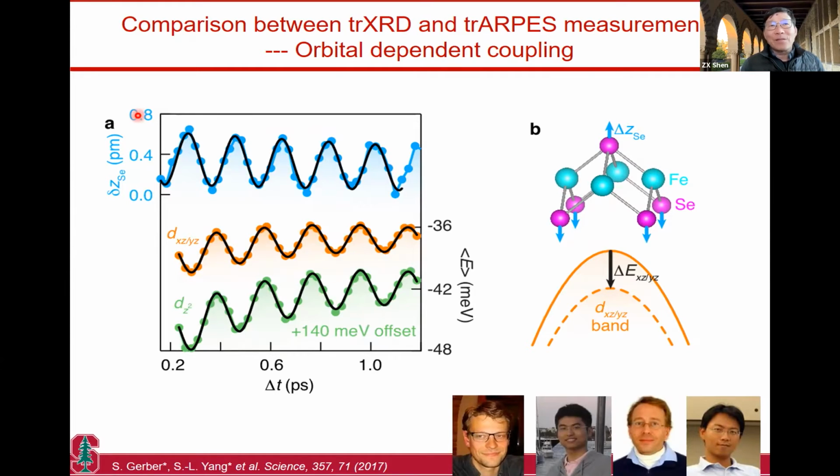So you better not change the lattice constant by 1% or more, because chances are if you change the lattice constant by more, you may well be studying a different material, not the material you intend to study. So given that constraint, and given the fact that this is less than 0.01 angstrom, and given the signal to noise, you can see what this technique can give to you. That's the power of diffraction.